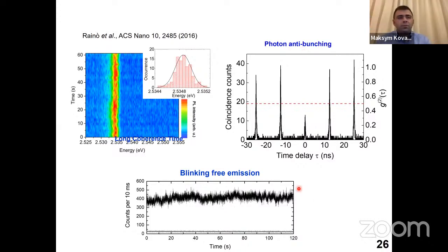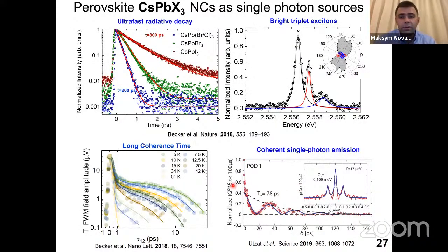So what this led us to, and let's look at some other important properties, which are very specific to perovskites. One is that at low temperatures, they're extremely fast light emitters, one of the fastest emitters that you can find. Unlike conventional quantum dots, which become much slower emitters as you cool them, so their radiative rates are in microsecond range because they begin emitting through the dark exciton state. Perovskites emit through the bright exciton state, also at low temperatures, and with sub-nanosecond radiative rates.